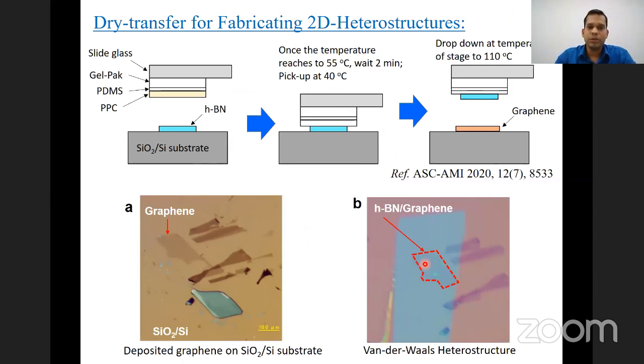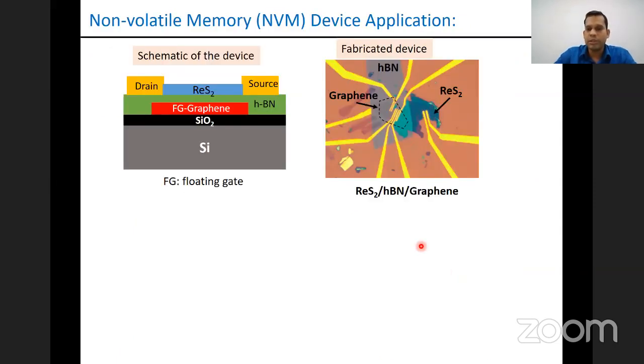So to start with, we again use a dry transfer technique. It is a very standard method, and we use a tip which consists of Gel-Pak PDMS and coated with PPC. And then we pick up HBN at a particular temperature, 40 degrees centigrade, and we deposit it on a graphene-coated substrate at 110 degrees. So we start with this graphene, which is on the silicon dioxide and silicon, and then we deposit HBN. So we have an HBN-graphene heterostructure. And then on top, similarly, we can deposit ReS2.